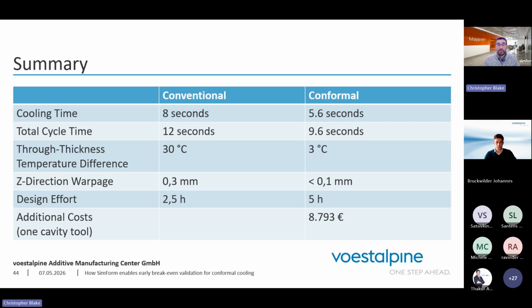So, just a summary of the simulation results here. In terms of cooling time, we can drop down from 8 seconds to 5.6 seconds. If we consider some assumptions around the mold closing, mold opening, and ejection times, we're dropping from 12 seconds down to 9.6 seconds when we get to conformal cooling. The through thickness temperature difference drops dramatically from 30 degrees to 3 degrees, and at least we looked at the Z direction warpage drops from 0.3 millimeters down to something that is basically negligible.